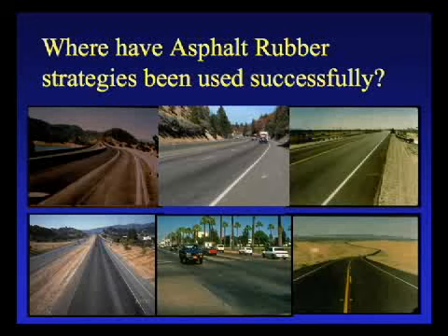So where has it been used successfully? Well, it's been used successfully just about everywhere. I could show you many, many projects at all different ages, but I'll just give you a little flavor of some of the projects and the type of things we did. This was a bridge deck up by Redding over Shasta, and there were actually two bridge decks placed, a very thin overlay on the deck. There was a problem with the underlying system that was placed. It had a lot of different twists to it for a bridge deck, and they had problems with it, so they put rubber on it. Unfortunately, because of the underlying material, the rubber only lasted about 5-6 years at this location, but it did alleviate that problem for at least 5 or 6 years.